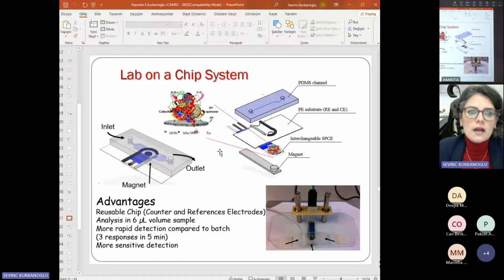And also, we tried to make this system using a Lab on a Chip system. We prepared small chips for that, and again put the same nanobiosensor here. Our idea was to use very small amounts of sample, small amounts of solution, and see if it is working or not. Again, we put a magnet under it, and just a 6 microliter sample was enough for us. We can see the detection of catechol here, then the inhibition by methimazole with this very small sample.